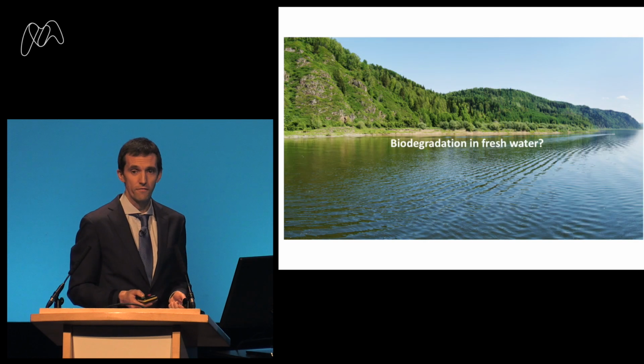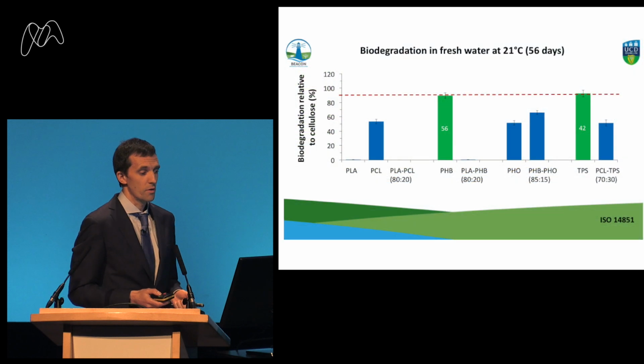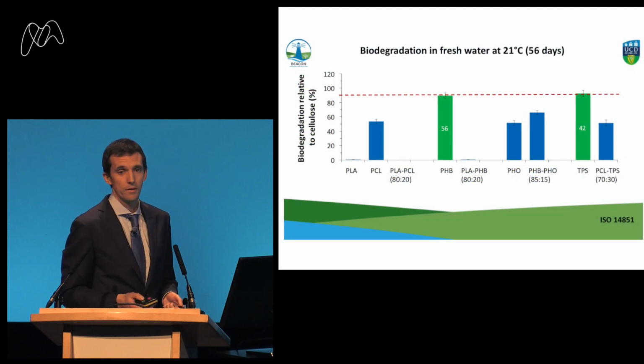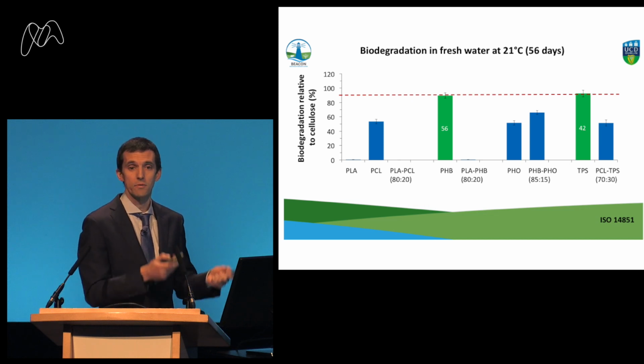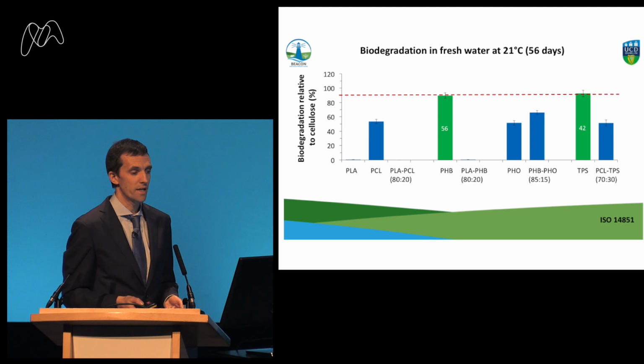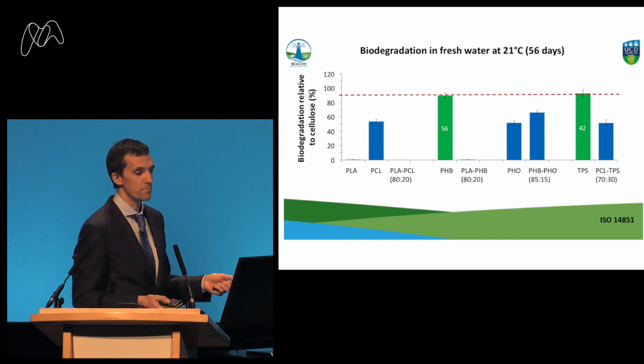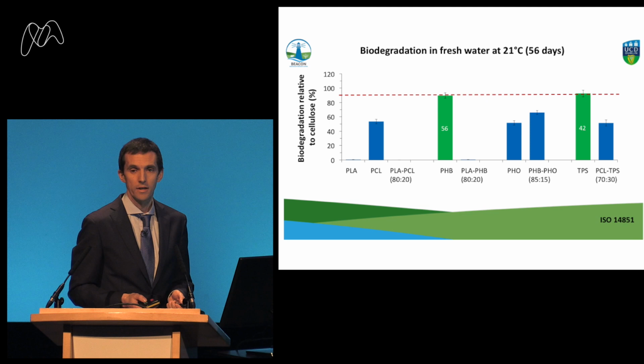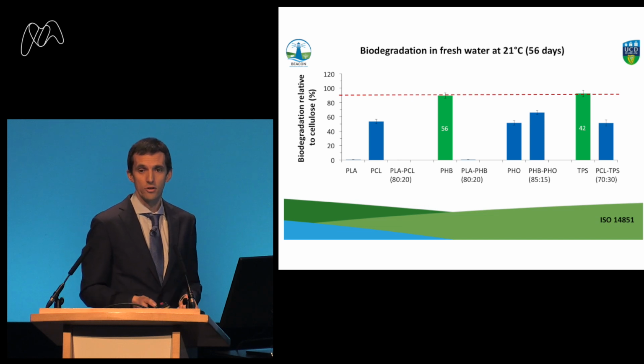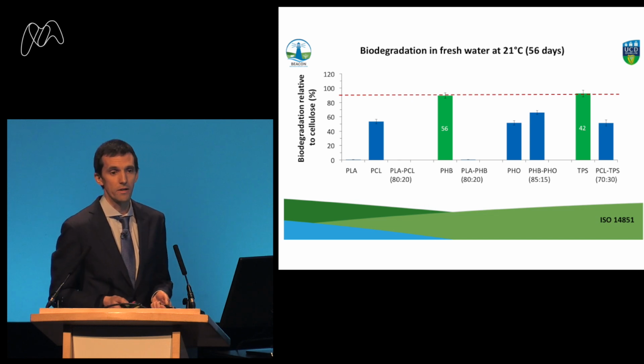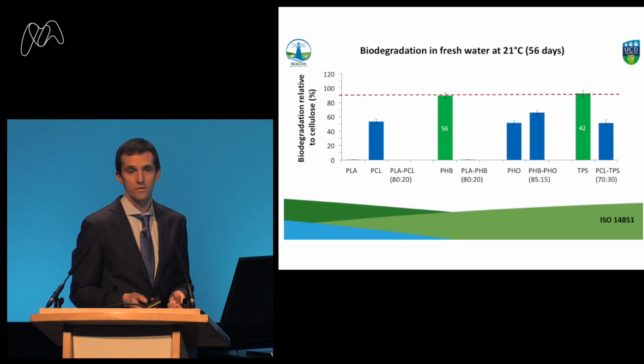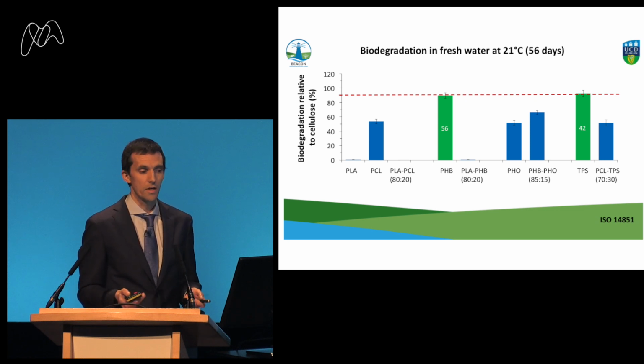So what about biodegradation in freshwater? What we see here again is PLA is very poor. PCL is not great. PLA blends with PCL, even though it's home compostable, industrial compostable, are not degrading at all in fresh water. PHB is making the standard just about at 56 days. TPS is also making the standard, but other polymers and polymer blends are not. So again, just like marine, in fresh water, these biodegradable plastics are not meeting the standards for biodegradation, but give them time, let's say 100 days, 120 days, and they will degrade.